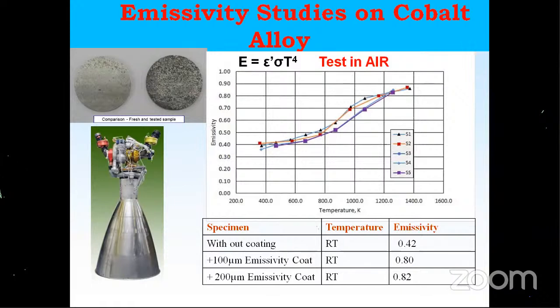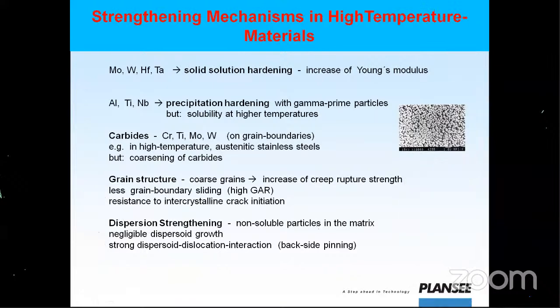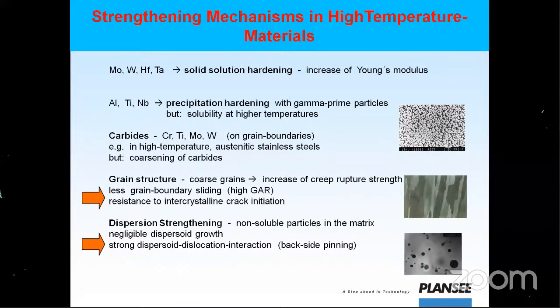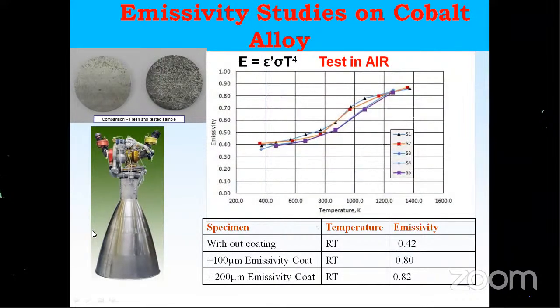This is very important. If you see any launch vehicle, you see a very dull surface outside. There are two kinds of cooling happening. One is regenerative cooling, where nothing is required. But with radiative cooling, when you have a single sheet and heat has to transfer to the atmosphere, we need a dull surface outside, which will give an emissivity as high as 0.8. Good. That is about the heat escaping to the outside.